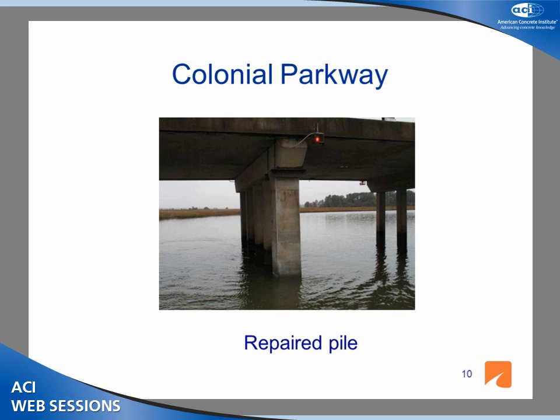The other thing we've done a lot of is, for the preparing of the surface, if you flood your forms before, we fill the forms up with water, especially if you've got to go a long horizontal distance. If you fill the form up with water, it serves two purposes. One, it wets your concrete surface, so that when your SCC is advancing, it's not losing water and drying out. You might start at 700 of flow and end up with something at 400 or 500, especially when you are repairing the bottom flanges of the beams. That's recommended to do. And the second thing, by flooding your forms, you'll see where it leaks, and then you can fix it.